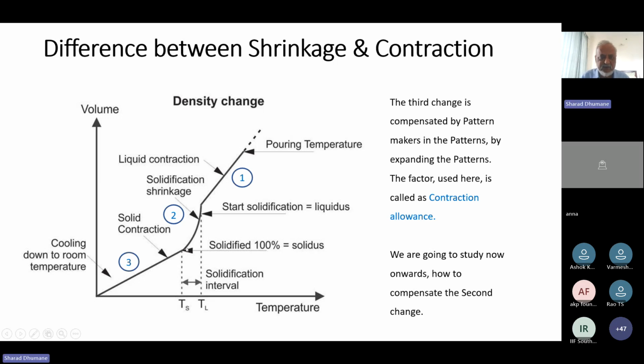From here to here, now it is solidifying, and since it solidifies in a temperature range, there is a solidification interval, and from here to here we can see there is a decrease in volume, and this volume is basically called solidification shrinkage, as we have seen earlier. The difference between liquid volume and solid volume is called solidification shrinkage, and that you can see here. Now, what happens after solidifying? It is still at a higher temperature, and when it cools to your room temperature, volume again comes down. Now, this we all know, and we call it solidification contraction. This we compensate by adding contraction allowance in your patterns.